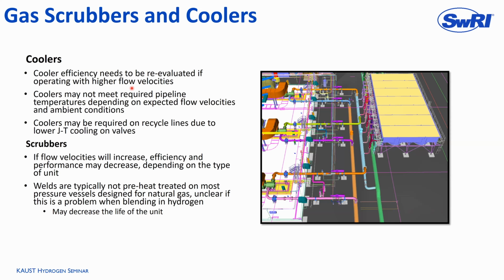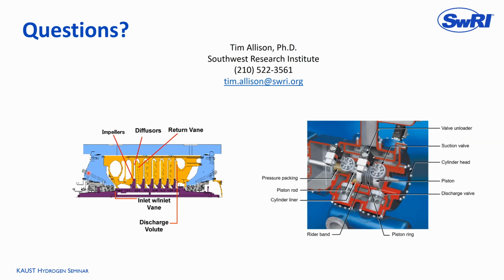So now you're hitting a double whammy on your coolers, where you've got higher flow velocities and you've got to achieve more pressure or temperature drop because you didn't get as much out of an upstream valve pressure drop. Scrubbers are also designed for flow velocities. So as we rapidly change flow velocities, we'll need to add scrubbers or at least evaluate their impacts. That's not really all of the impacts, but it was what I could do in about 15, 20 minutes.